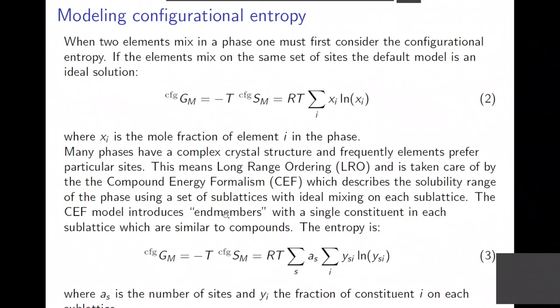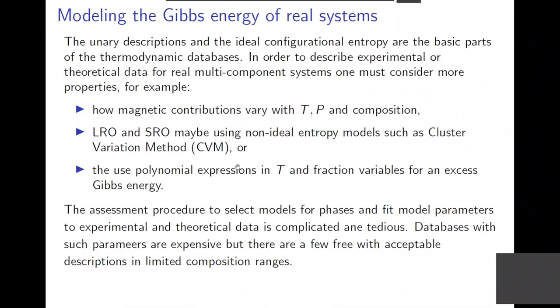To go to short-range ordering, one needs to have modeling with clusters, but that is usually too heavy for the current modeling with multi-component systems. You can do it for two or three elements, but for higher order systems, it's too heavy computationally. So to go to description of real systems, the current CalPhad modeling includes excess functions for the ferromagnetic transition. One uses long-range ordering for intermetallic phases, and one uses simple polynomial expressions in the composition and temperature for the excess Gibbs energy. So those are what is contained in the databases of a CalPhad model.